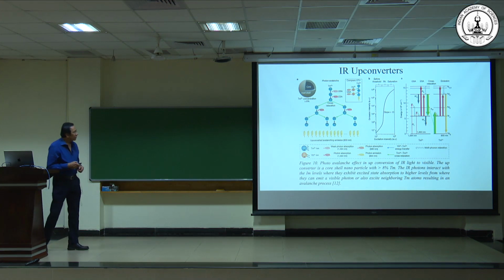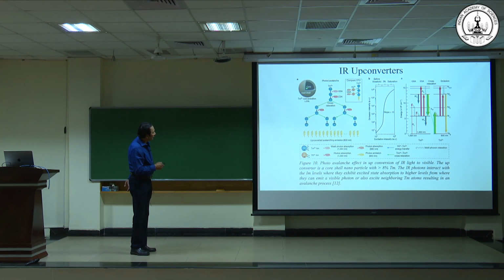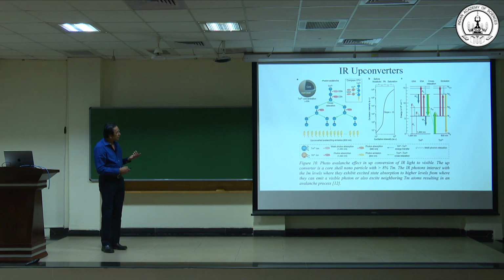And the way you do that is, you take a nanoparticle, and these nanoparticles are doped with a rare earth element like thulium, for example. Then this core shell nanoparticle does an amazing job of converting infrared intensity into visible light. This light, which is anywhere between 1 to 1.5 microns, gets converted into 800 nanometers. There's a power law here, like a 15th power law, and this is some kind of an avalanche effect where every thulium atom excites the next thulium atom in the next sphere, etc. So how do you produce these nanoparticles, right?